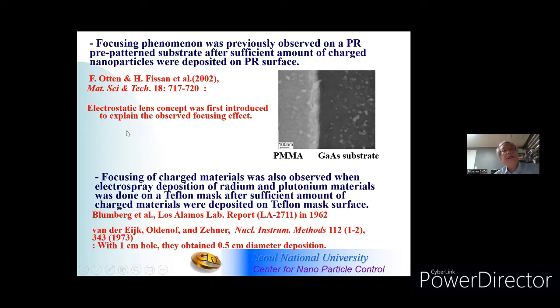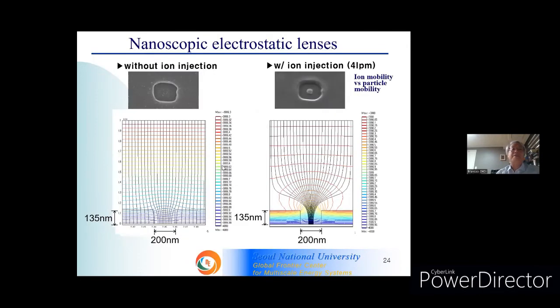And they introduced electrostatic lens concept to explain the observed focusing effect. And in 1962, the focusing of charged material was also observed when electrospray deposition of radium and plutonium materials was done on Teflon mask, after sufficient amount of charged materials were deposited on Teflon mask surface. But in our method, we use ions, not charged particles, to generate nanoscopic electrostatic lens.